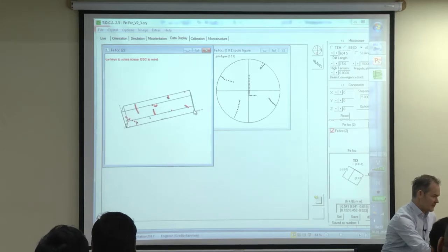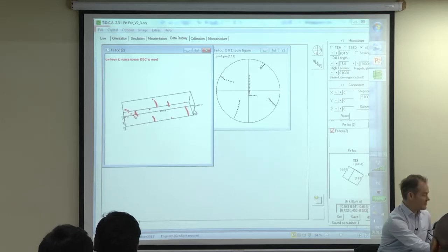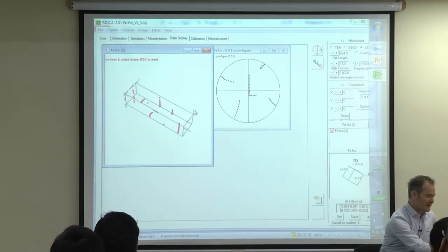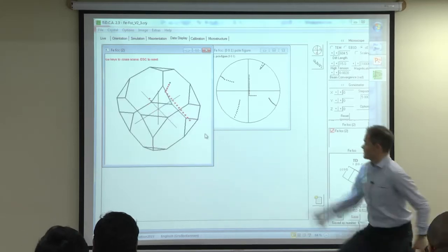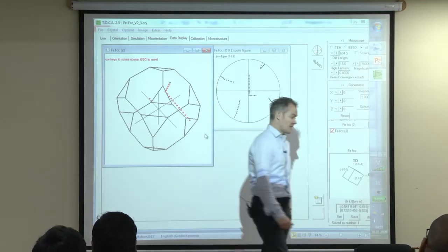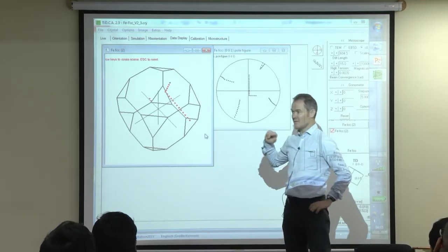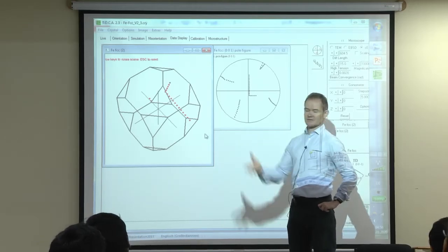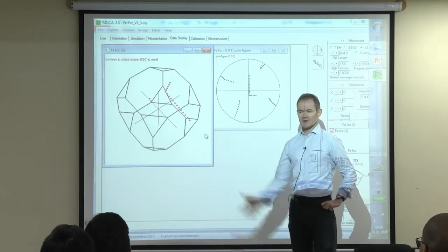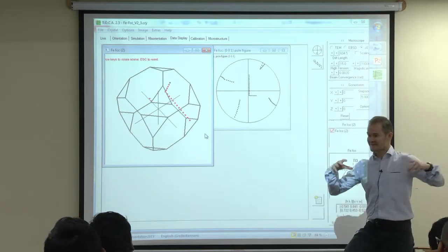And you see now we have not only 3 fibers, 3 lines corresponding to this, but even a number of points. While in Rodrigues space, once again, in principle you just have one straight line. It's actually easy. Rodrigues space is something beautiful. It's nice to handle. And the OIM software offers you the same possibilities to handle Rodrigues space as the Euler space. Just traditionally, historically, Euler space is more used, and therefore that's probably the reason why everyone is stuck to that.